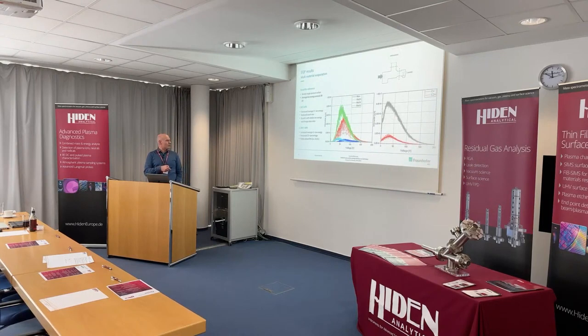Now, if you go to the molybdenum one, it's only 5 atomic percent in it, which is not much, but it has a huge effect. And here we see some movement to the right side and a very large ion flux in the carbon plus. Here it's voltage, which means you have to scale this, of course, multiplying by 2. And you have to do a measurement at each charge state of each element. Then you do the scan, or set up one scan where you do all of this at a time. Here, if you have the voltage, you have to multiply this by the charge. The blue one stays the same, and the other ones go further and further to higher ion energies.